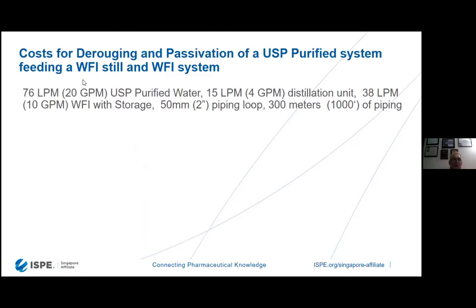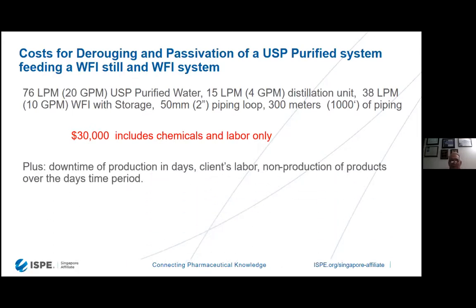So if we're looking at a fairly small system running at 76 liters per minute, or 15 liters per minute in the distillation unit, going out to a 38 liter per minute WFI water storage with only a 2-inch piping loop running about 300 meters, what is the real cost of doing derouging passivation, even on this smaller system? Well, the actual cost in dollars, including chemicals and labor only, is about 30,000 US dollars. If you add in downtime of production in days, the client's labor, the non-production of the products because the system is down and can't produce product, it can get very expensive very quickly. For a small system, we're talking about $50,000 and higher.